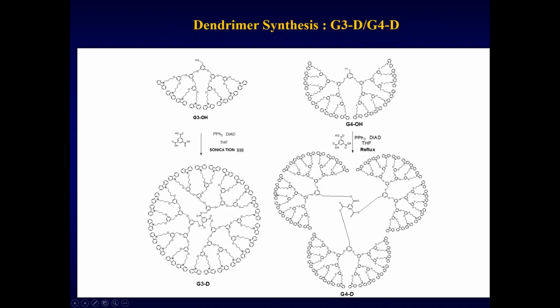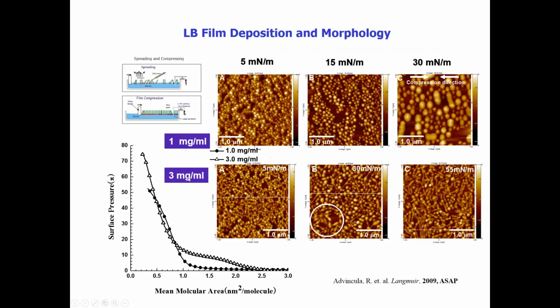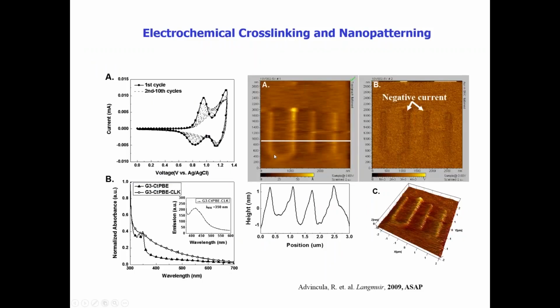These are electrochemically active, as proven here by the CV diagram. But again, electro-nanopatterning can be manifested with these still electrochemically active dendrons. And we were actually interested in observing the individual cross-linking of these dendrimer units, as shown here. So in an intramolecular fashion, these carbazole units can link up to form this type of globular structure. We have followed this indirectly with absorbance and NMR results. But what's interesting is that AFM is an important tool for us to directly visualize this cross-linking process. So here is the image before and after.